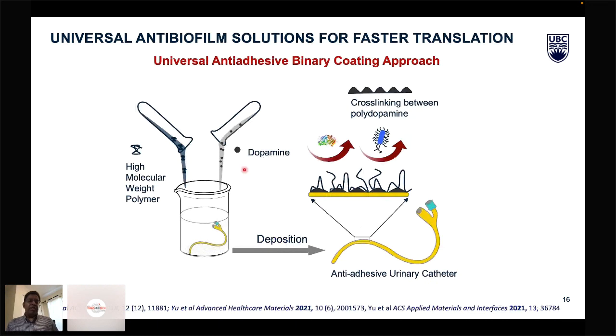Using the principles we learned, we came up with another universal anti-adhesive coating, which is a very simple process. We mixed two different polymers, a monomer and a high molecular weight polymer, together and polymerized in situ to generate a coating, which can be applied on the surface using either dip coating or spray coating or any other coating method. It's a really remarkable method in that it could coat any surface within a few minutes to a couple of hours, and we can generate a better coating.